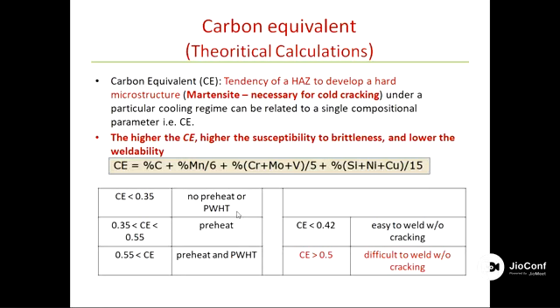It means there is no danger of hydrogen embrittlement or delayed cracking, or any issues related to cold cracking. But if your carbon equivalent ranges from 0.35 to 0.55, you need to go for preheat. If it is more than 0.55, preheat and post-weld heat treatment both are mandatory. And if the CE value is more than 0.5, this steel is difficult to weld without cracking.